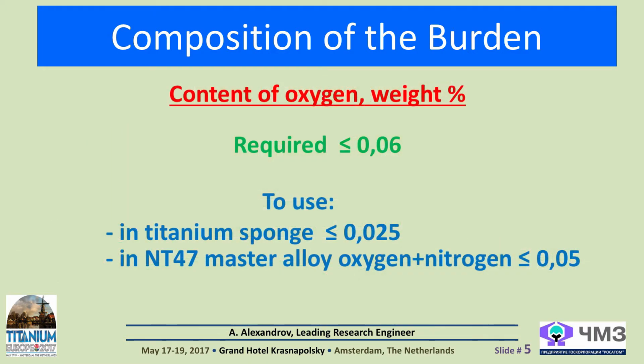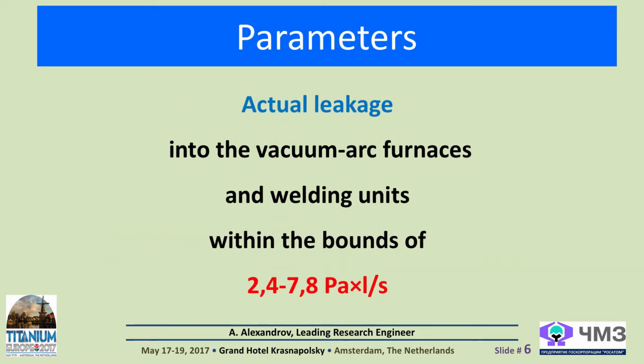It can be achieved by selecting the charge components and setting the melting parameters. For this purpose, lots of titanium sponge with an oxygen content of not more than 0.025% and lots of niobium-titanium master alloy with a sum of oxygen and nitrogen content not exceeding 0.05% were chosen. These components contain the greatest amount of oxygen in comparison with other master alloys. Among the parameters, it should be noted that the actual leakage into the vacuum arc furnaces and welding units was limited within the bounds of 2.4 to 7.8 Pascal liters per second.